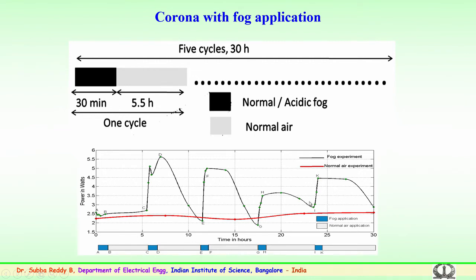So, the red color shows the experiment which has been conducted only with normal air. There is no fog during this experiment of 30 hours. For comparison purposes, the sample is allowed only normal air and electric stress. The voltage is applied and the experiment is conducted. You see that there is not much variation over the period of 30 hours, only a very marginal increase is noticed,